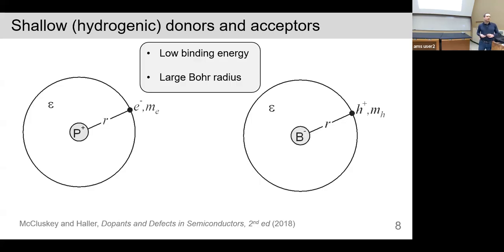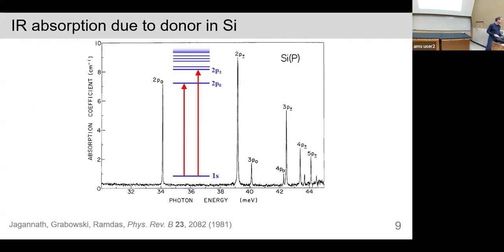And then you can also have acceptors doing the same thing. So you have a negatively charged boron, which has acquired an electron from the valence band. And that hole then orbits around the boron. And so it acts like anti-hydrogen, if you will. Okay. So just like the hydrogen atom, these impurities have 1s to 2p transitions that you can see with optical spectroscopy.